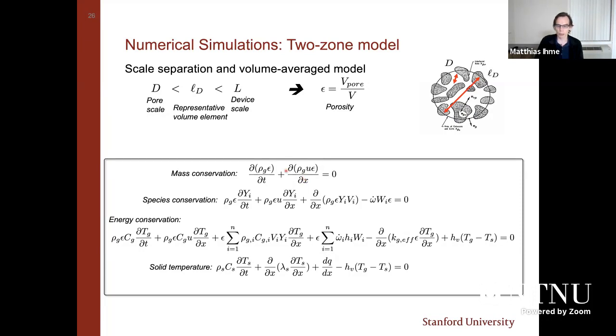And just to explain this equation a little bit more, the first equation describes the conservation of mass. The second one is a combustion equation where we are describing the chemical species. Y is the species vector. And the epsilons here that you see is the porosity, comparing the pore ratio over the representative volume. You're recognizing here a chemical source term. We have an energy equation here where we have a contribution of the heat release by combustion. And we have a heat exchange term by convection.